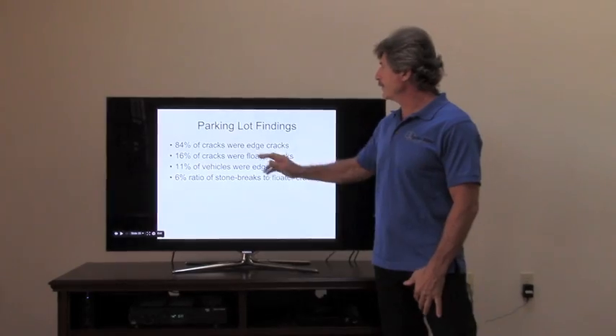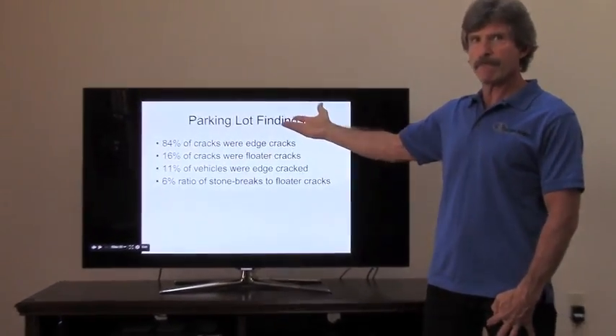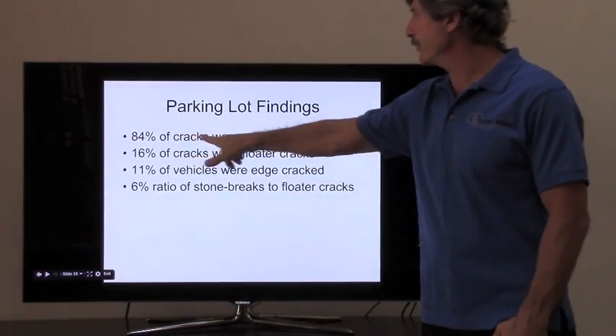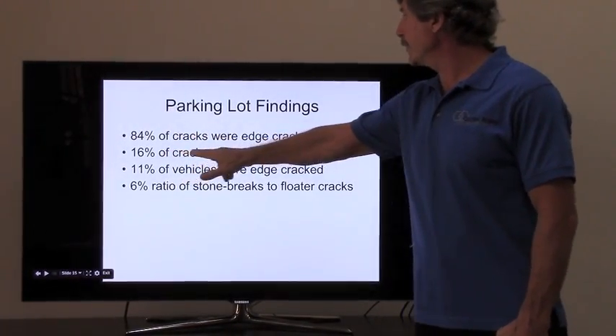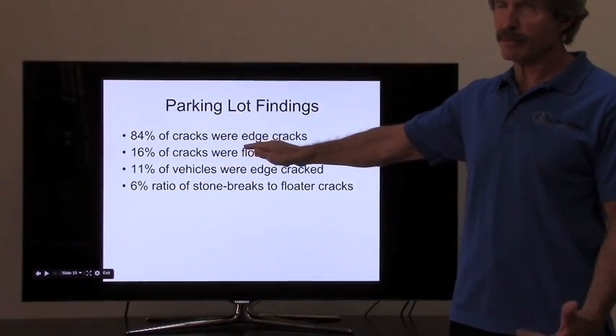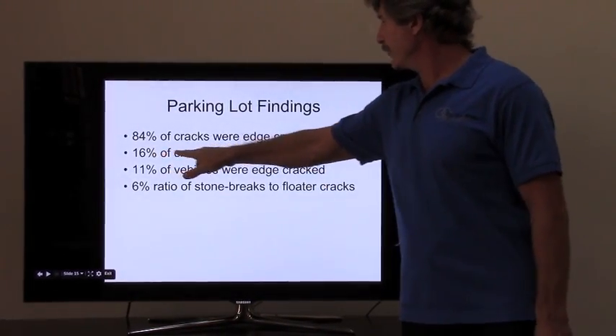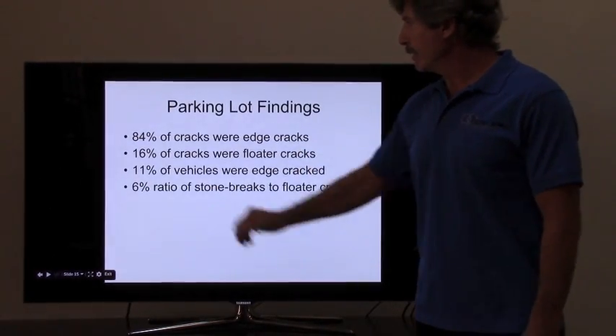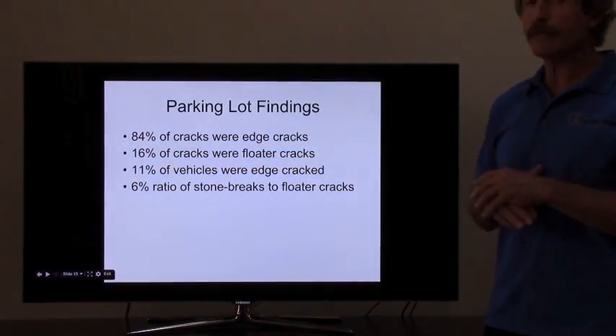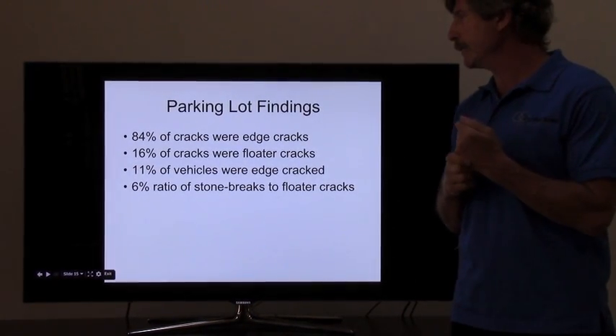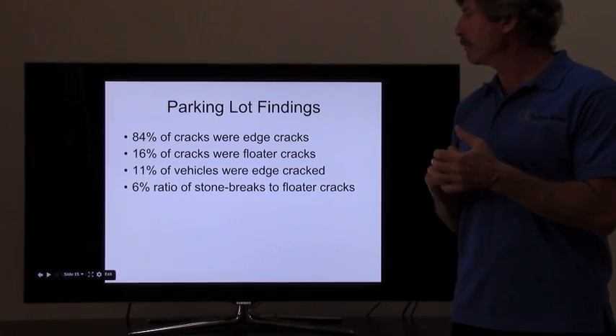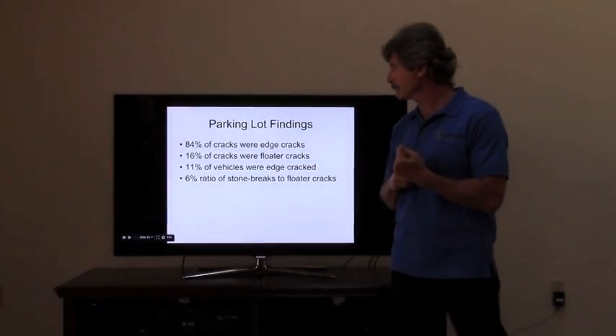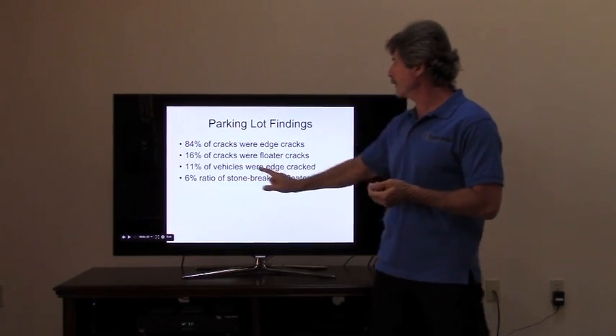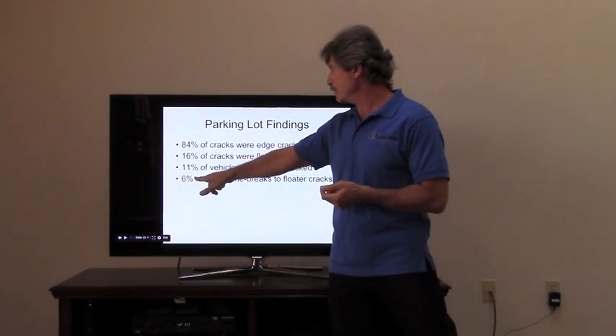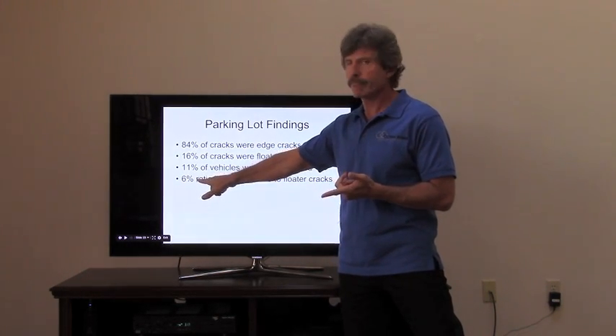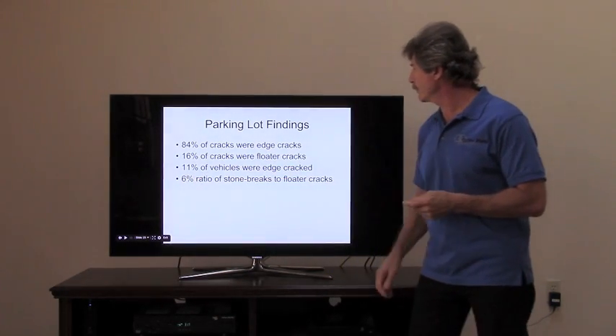What the parking lot findings found is that 84% of cracks were edge cracks. And we saw in 2014, 95% of our cracks were edge cracks. 16% of cracks were floater cracks. This is back in the 1990s. Now it's 5% are floater cracks. 11% of the vehicles were edge cracked. Again, this was in the 1990s. Might have even been 2000. But 1 out of 10 vehicles have an edge crack. And the ratio of stone break to floater crack was 6% back then. Now it's about 2%. Yeah, it was 2%, I think. That's the ratio of stone breaks to floater cracks.